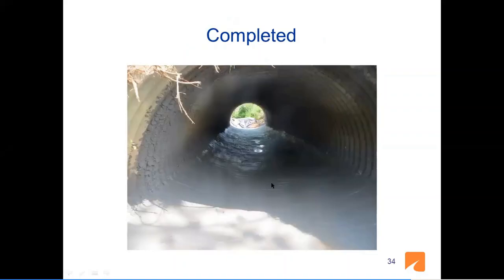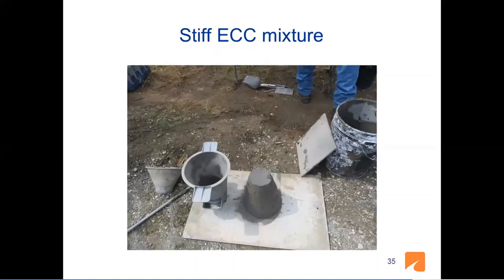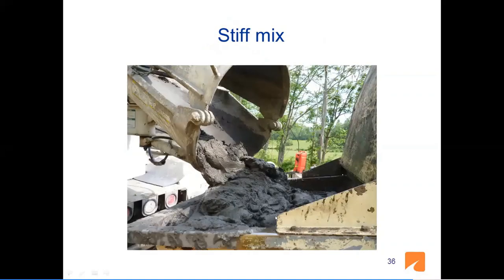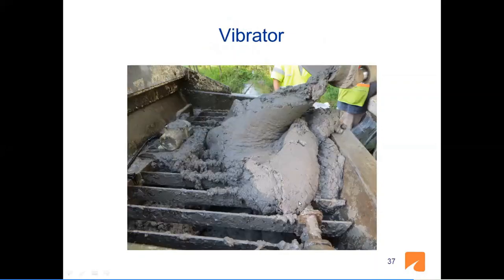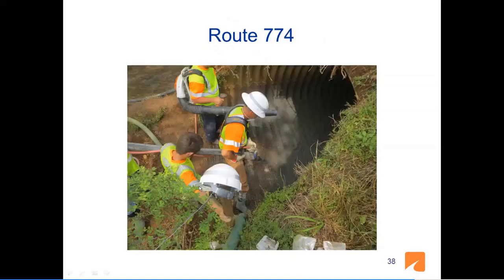Then in the spraying, they told us that they would prefer, rather than a wet mix, a dry mix for spraying so that it would stick better to the metal culvert. Then we did this stiffer ECC mix, as you see, stiffer mix, and then we tried to put it through the grate. You see the stiff mix didn't go through the grate easily. So then they brought in a vibrator. You see a vibrator here. With the help of the vibrator, the stiff mix was able to go through the grate easily.